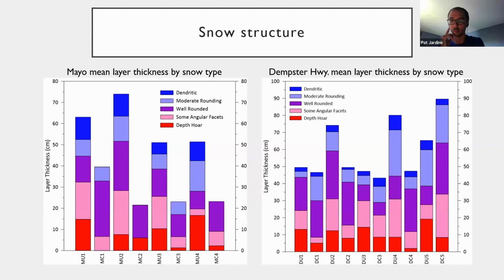The dendritic snow and depth hoar are the softest snow types at both locations, and this made them the most susceptible to compaction. In Mayo, every snow type had less accumulation at the compacted plots, except well-rounded snow, which increased in thickness. The dendritic snow layer was mixed in with surrounding snow, so there's almost nothing left. And there's also no more depth hoar at the compacted plots after the first month. The reason there's some red there is just because the first month's impacting the average. At the Dempster sites, the only other snow type with significant reduction at the compacted plots was depth hoar, while there was an increase in well-rounded snow.